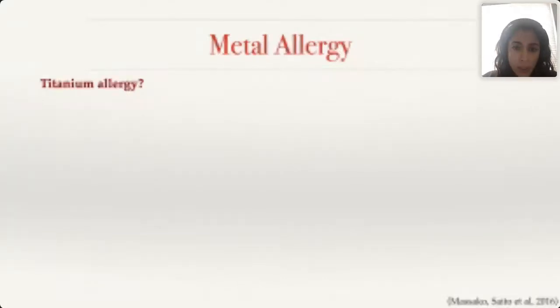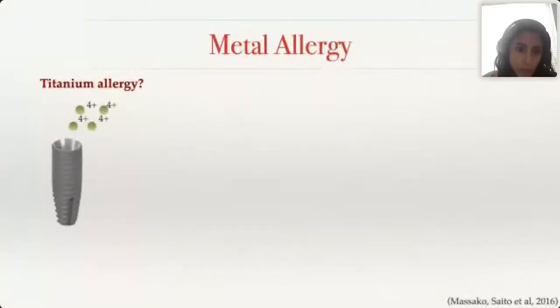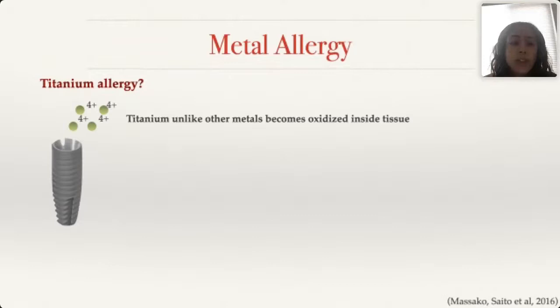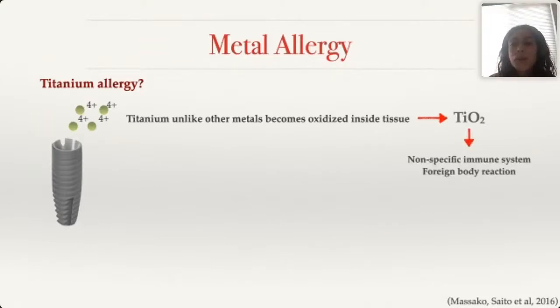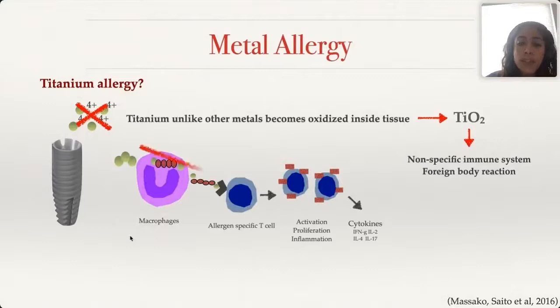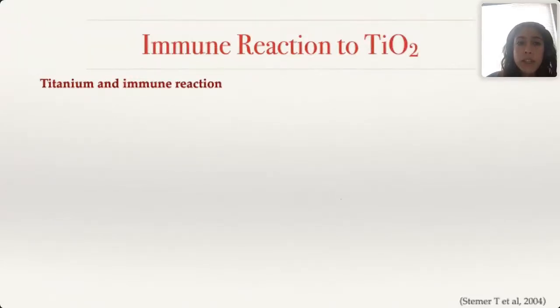What about titanium - can we have a titanium allergy? With titanium, we actually do not form free ions. Titanium becomes oxidized when exposed to the environment, forming titanium dioxide. If there is any reaction to the titanium dioxide particle, it's going to be a non-specific immune reaction through foreign body reaction, because we do not form ions, only titanium particles. So this process of specific type 4 immunity does not apply to titanium, and we cannot really have a titanium allergy.